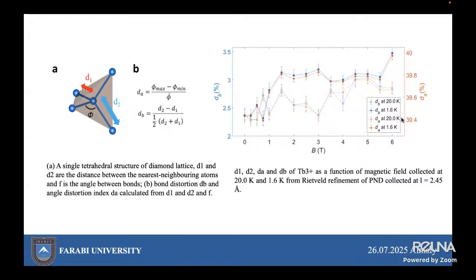We found the terbium ions form a stretched diamond lattice, which undergoes increased bond and angle distortions under the magnetic field at 1.6 Kelvin, suggesting quantum magnetoelectric coupling. With increasing field, the system transitions from antiferromagnetic to canted antiferromagnetic and eventually to paramagnetic order.